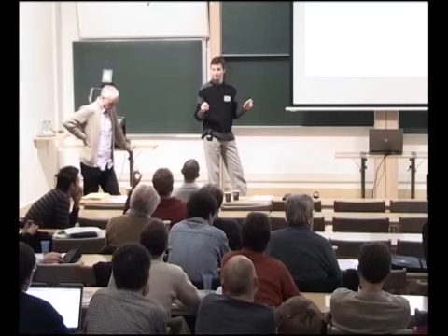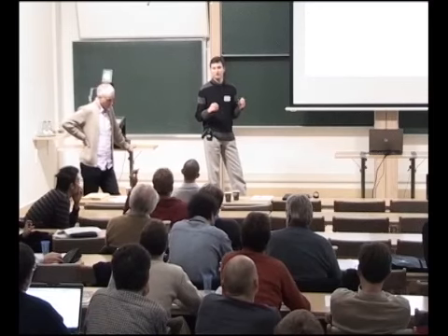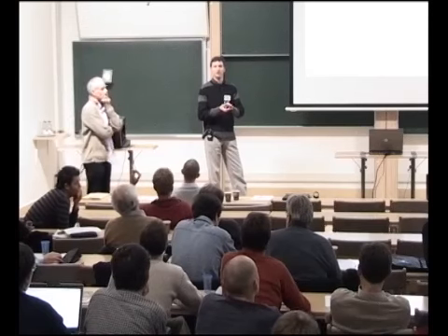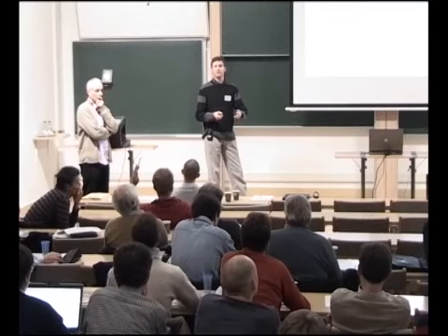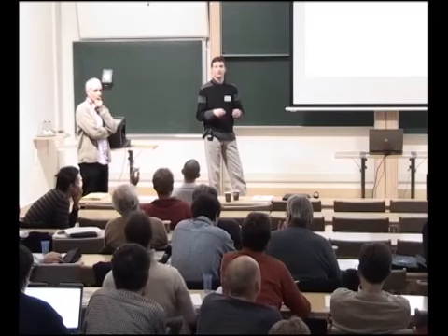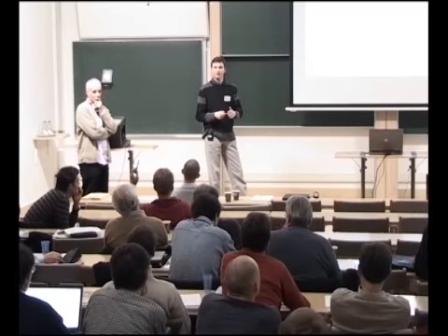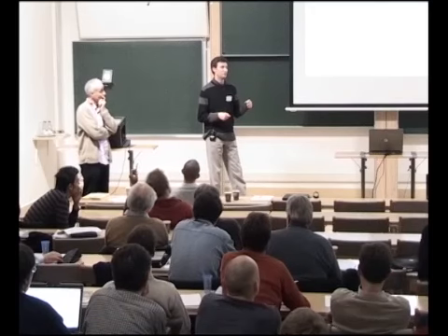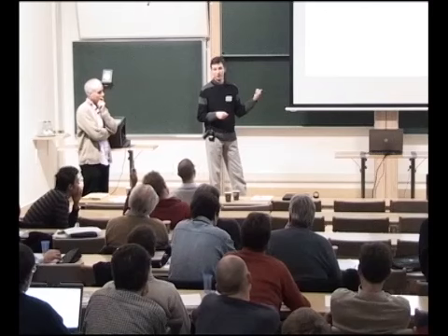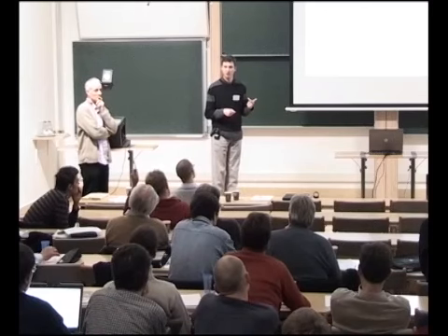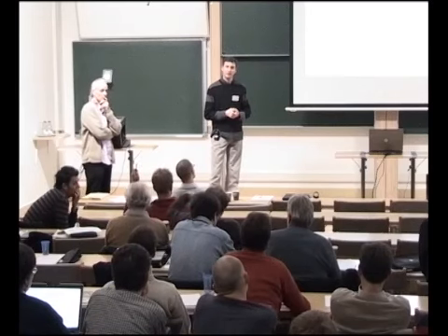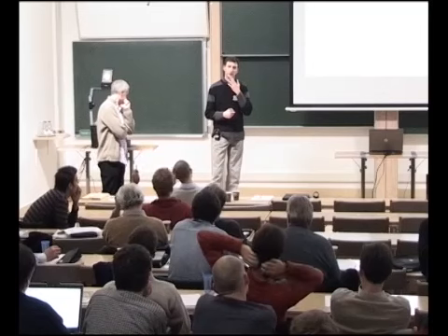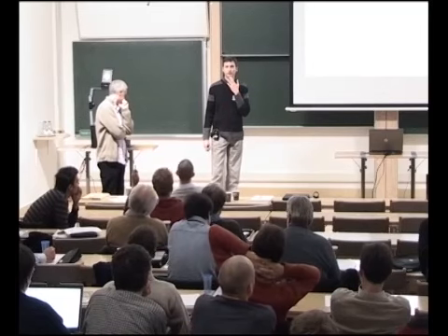Which is not the case in the Herschel-Bulkley parameterization in 3 dimensions. The problem of the 3 dimension is that if you want to have a very wet foam, you would need to have very small bubbles, because otherwise, if you have a large sample, all the water would flow down, and you would have liquid fraction that would vary through the sample. That would be very annoying. So we have either to get rid of gravity or to have very, very small bubbles to perform experiments in the wet regime in 3D.